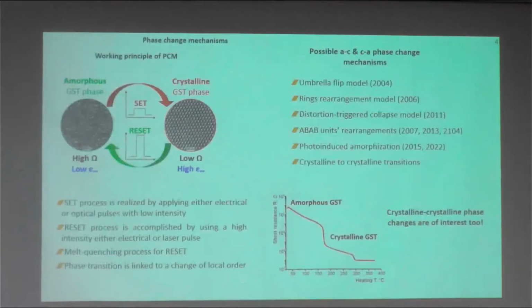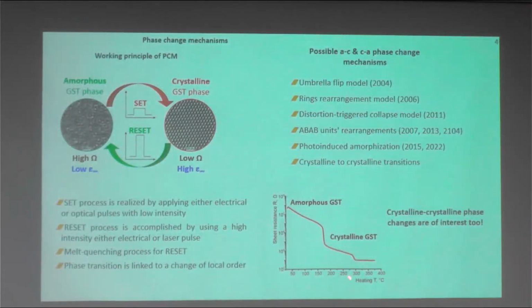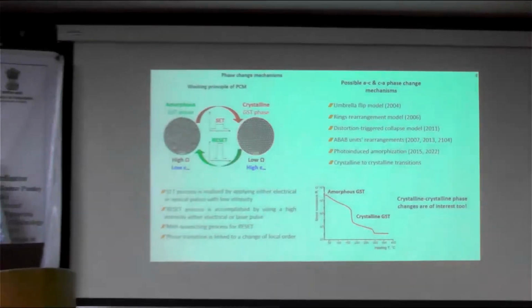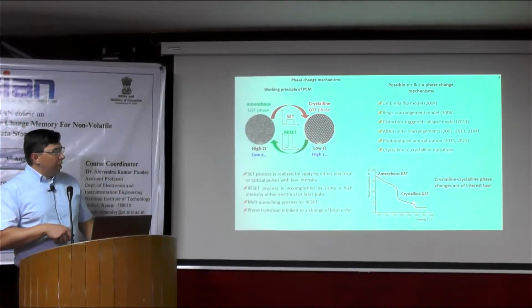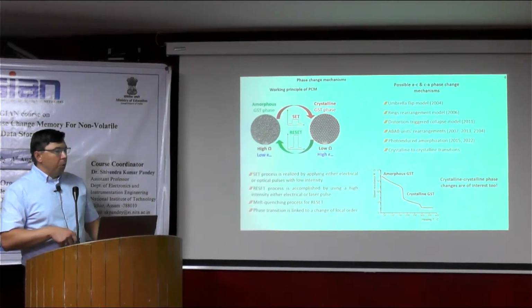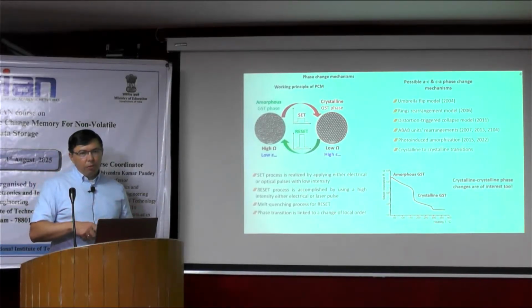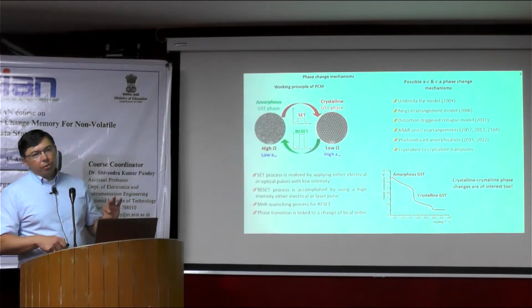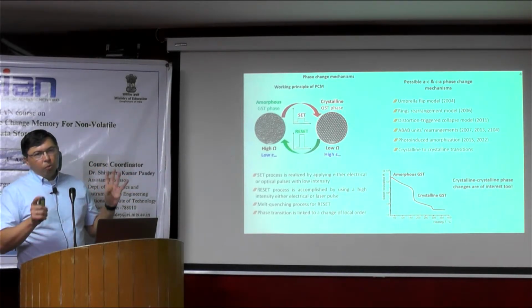If you remember this RT measurement, it starts from here, maybe a little bit larger temperature here, but it's in the range between 170 and 200. Can be a little bit extended, but the problem here, we will discuss that: at some temperatures you have a mixture of vacancy ordered and trigonal phase. Because after 220, we observe the formation of both phases.